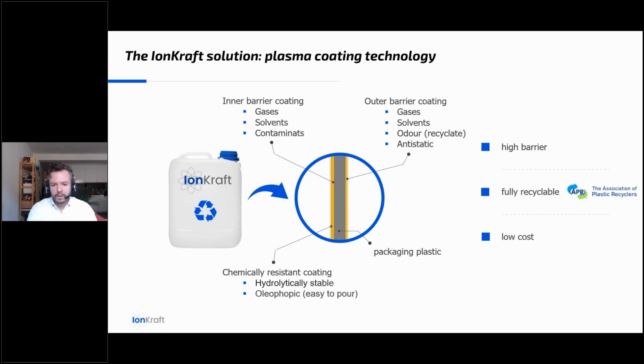And the coating on the inside has one layer which stops gases, solvents, and basically any other molecule that should not be moving through those packaging walls. And the chemically resistant top coat provides the necessary stability against alkaline and acidic environments. And this coating even has an oleophobic surface, which helps to reduce residue of oily liquids in the plastic container. So an easy to pour solution. I will later show you a visualization, a picture of this functionality.